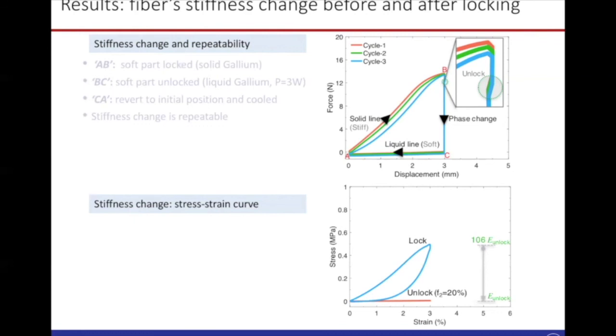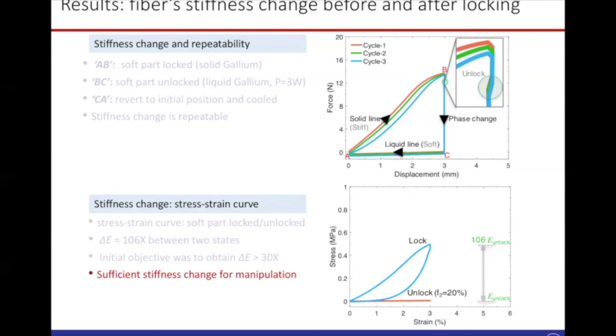Now, in order to quantify the amount of stiffness change, we use the stress strain curve with the soft part locked and unlocked. So the blue curve indicates the stress strain curve when the soft part is locked, and the red curve indicates the stress strain curve of the hybrid fiber when the soft part is unlocked. As you can see, there is a difference of around 100 times between these two extreme states. So initially our objective was to obtain at least 30 times in the stiffness change, but this could give more than 100, and it should be sufficient for manipulation application.